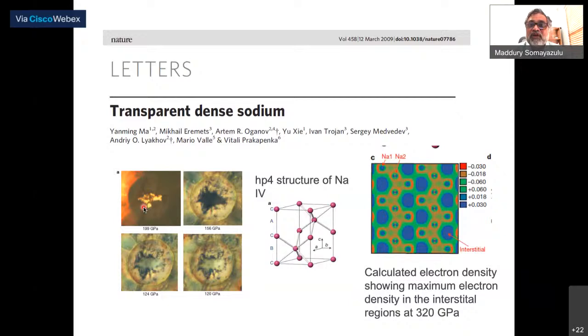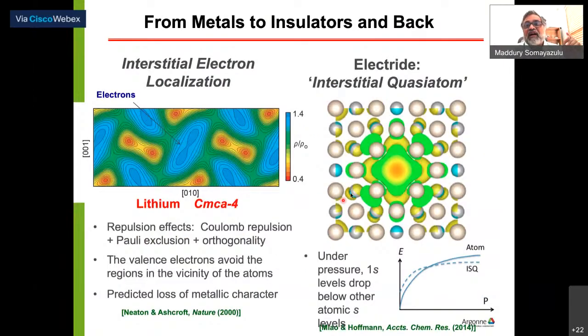So in effect, this is almost counter to what I was talking about earlier, but it tells you that something more interesting is happening when you bring atoms together, or when you increase the pressure on materials. In this case, you form what are called interstitial quasiatoms or electrides. It's almost a paradigm-changing kind of understanding of physics, in that in a very simple way, the repulsion effects take over.